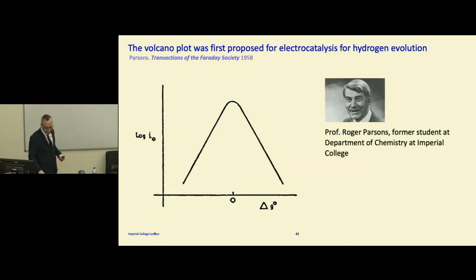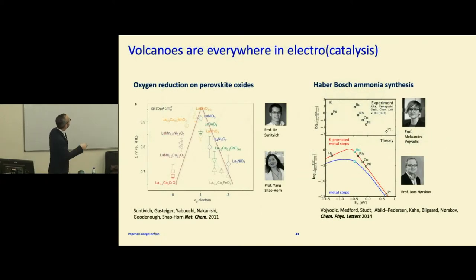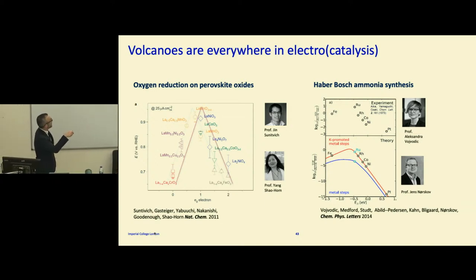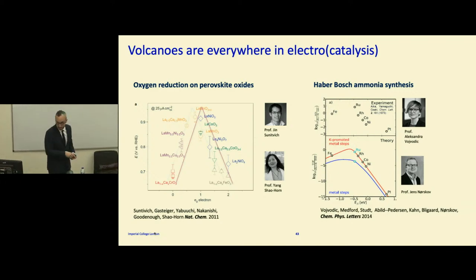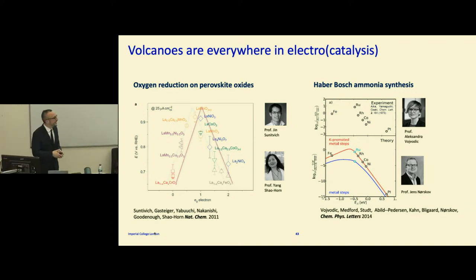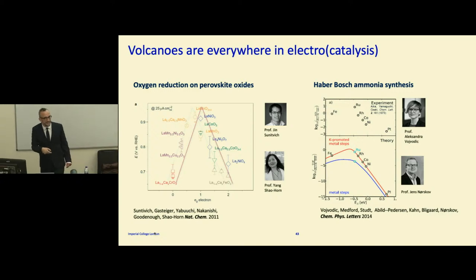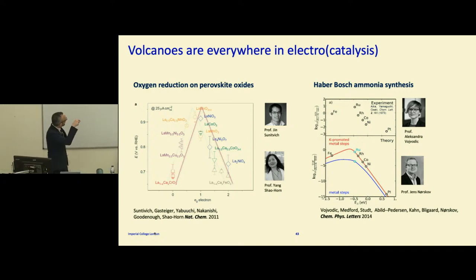So now, today, volcanoes are everywhere in electrocatalysis or catalysis at large, even on oxides here for oxygen reduction, previously I was showing metals, and also for the Haber-Bosch process. You know, ruthenium works best because of moderate binding to nitrogen. So usually when you look at these volcanoes, what people typically do is they either have theoretical activity, as a function of a theoretical binding to reaction intermediates, or they have a more indirect experimental descriptor on the x-axis.